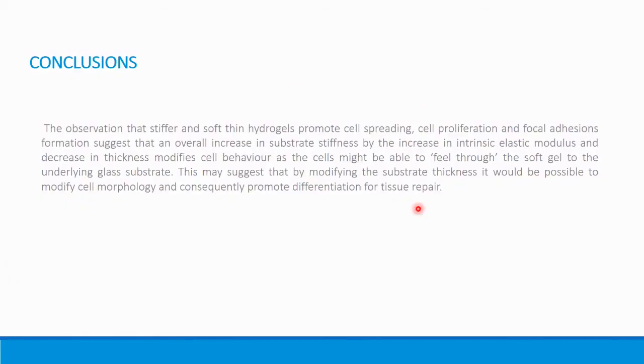So far, we have confirmed that substrate elastic modulus and substrate thickness promote cell spreading and influence cell morphology and focal adhesion formation. And more importantly, we found that bone marrow stromal cell proliferation and osteogenic differentiation is linked to depth sensing.